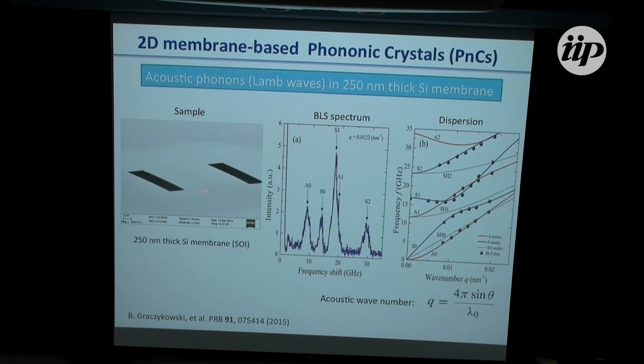If one varies the angle of incidence on a sample, you have the projection on the plane, and that allows you to measure the different wave vectors. So these are the various points. They have been measured at different angles, and they map the dispersion relation. So we have a very good understanding of which peak belongs to what symmetry and to what band. So we have symmetric, asymmetric modes, shear, dilatational, you name them, right?